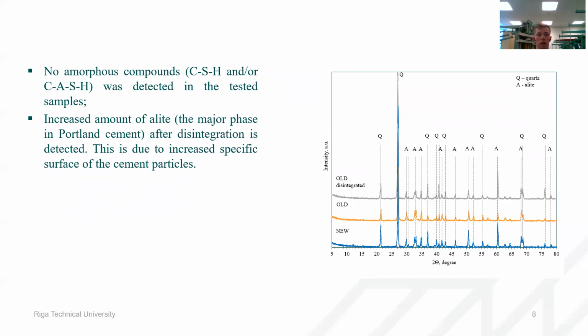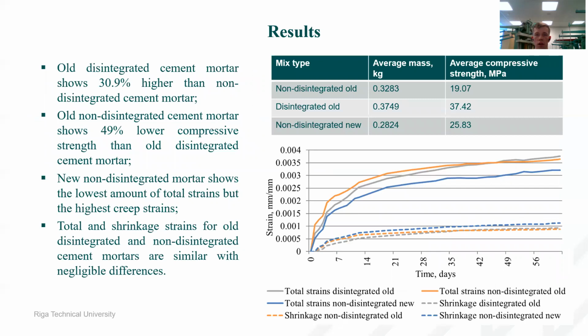If we look into XRD spectrometry results, we can see that no amorphous compounds were detected in the test samples. So we can surely say that the old cement was placed in an environment that wouldn't have high moisture content, therefore the hydration hasn't happened for it. Furthermore, we can see that for the disintegrated specimens, the amount of alite is higher than for all the others. And basically this is because of the milling, and because of that, the specific surface of the cement particles is increased, and therefore the higher alite amount is in the composition.